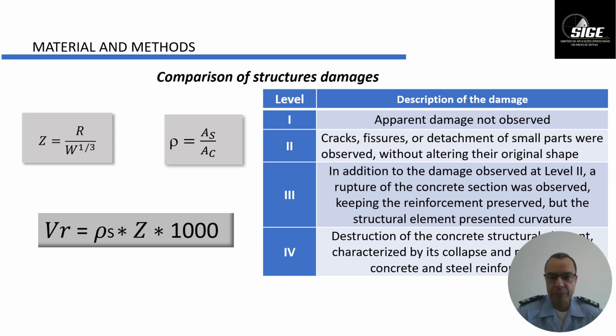Level 1, apparent damage not observed. Level 2, cracks, fissures, and detachment of small parts are observed without altering their original shape. Level 3, in addition to that damage, we can see the rupture of the concrete section, sometimes keeping the reinforcement preserved, and the structural element presented curvature. Level 4, the complete destruction of the concrete structure, with the rupture of the concrete area and also the steel.